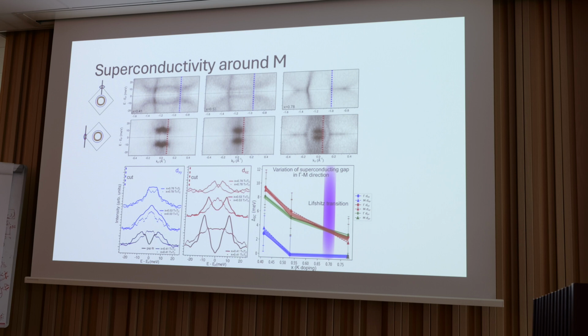Now we can look at superconductivity around M. So the top row is in an experimental geometry to best see the DXY band. The second row, we look for the XZ pocket, and what we see is that we actually can resolve a gap on the XY band, which I think previous literature has not been so clear about, being able to see both band gaps for both electron pockets. So I think we see two gaps on the XY and XZ.